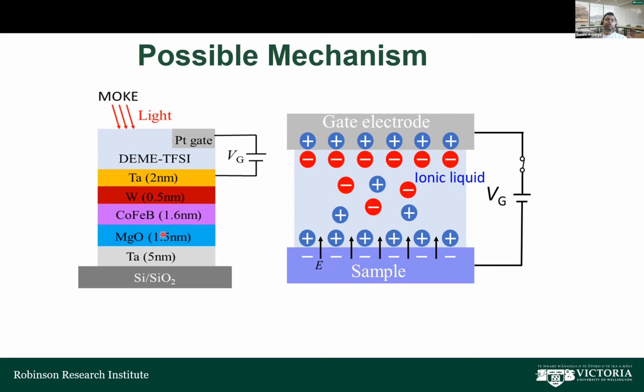We know that the perpendicular magnetic anisotropy in the CoFeB stack is due to the interface between the tungsten and CoFeB. That is because due to the shape anisotropy, CoFeB always tries to show the in plane anisotropy. But when the CoFeB thin film is really thin, like 1.6 nanometer here, the interfacial anisotropy overcomes that shape anisotropy, and the anisotropy becomes out of plane. But when the interface gets disturbed by the ionic liquid, because of the migration of the oxygen ions, now the thin film stack becomes in plane. On the other hand, when we apply the negative voltage, again the oxygen will migrate back to this interface, and we get to our previous pristine state.